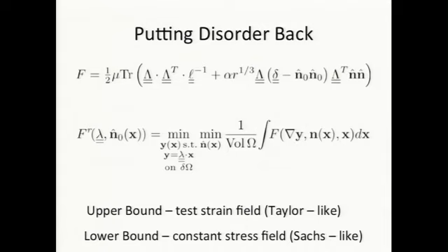Now, this is very hard to do anything sensible with, principally because I haven't been willing to say anything about the structure of this n0 field. So the form we'll probably want to look at now, sorry, this lambda here should be a capital lambda. We want to take this energy, integrate it over the volume of the elastomer, subject to the boundary condition that we've got some displacement on the boundary, and then minimize it over all internal displacements. So subject to capital lambda being a gradient of a displacement field, so being a kinematically compatible displacement, and we also need to minimize over all n of x.